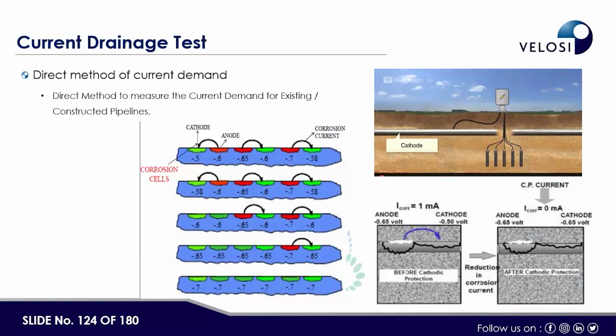So with this natural potential survey, we then apply the current slowly, starting with 2 ampere current, and we see how the potential changes at that location. The moment the anode and cathode potential differences are minimized, it means that current is required. Or we have the NACE applied 850 millivolt. After applying the temporary CP system, if we measure 850 millivolt in every location, then we can measure how much current is required. For example, one contractor already installed a pipeline and we measured the potential, which is less than 850 millivolt. So he keeps on applying the current until he achieves a minimum of 850 millivolt wherever we measure. That we call the current drain test.